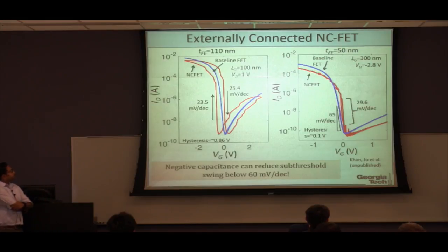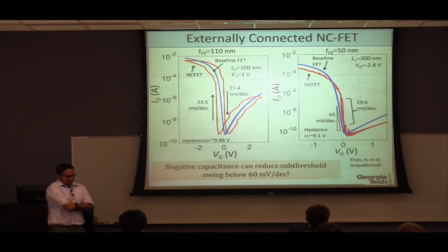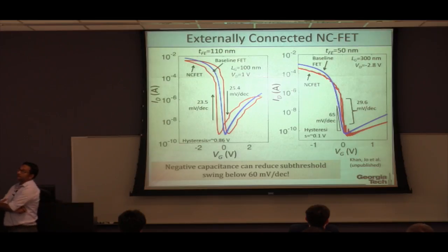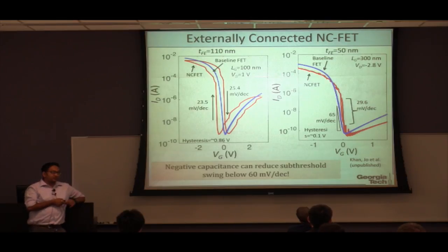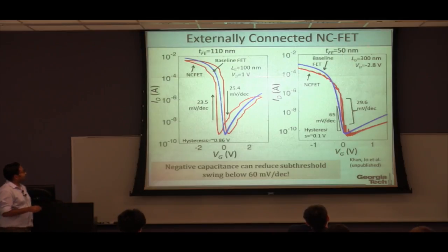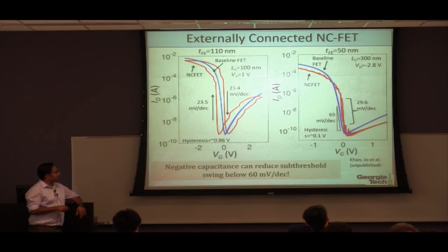All right. So in the previous slides, what we have said is that as we increase the ferroelectric thickness, the subthreshold swing increases, and at some point we get a hysteresis. In the previous experiment, we used a 600 nanometer film. Then we reduced the thickness to 110 nanometers, and it shows that the hysteresis has gone down significantly. And then when we go to 50 nanometers thickness of ferroelectric, we see that the hysteresis has gone down even lower. And here, the hysteresis is less than 100 millivolts.